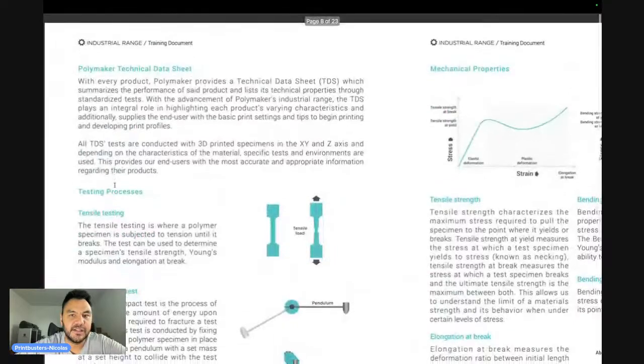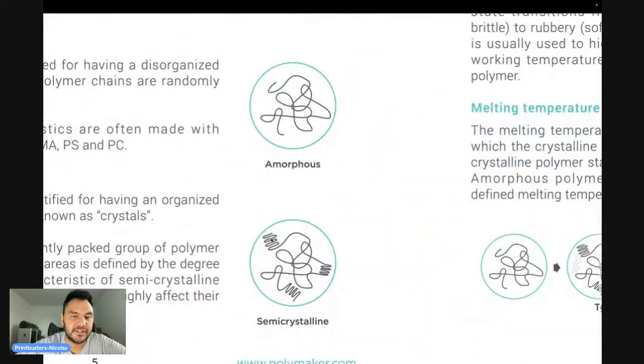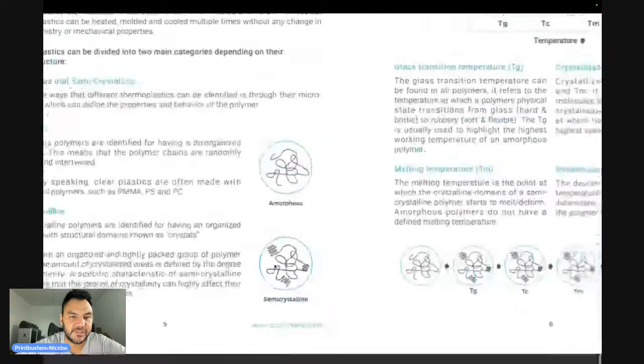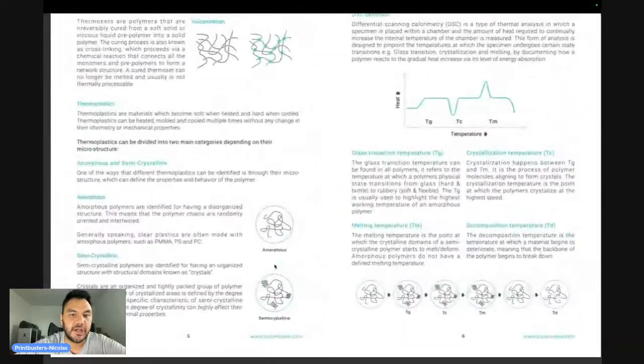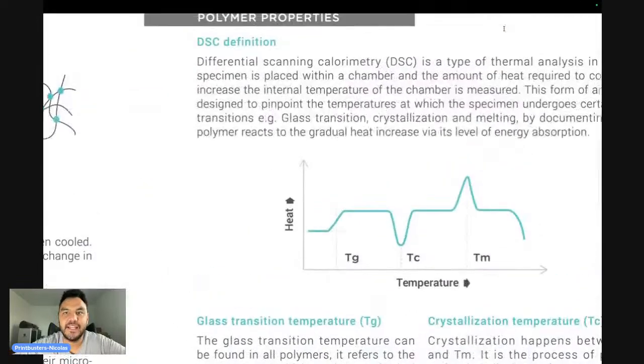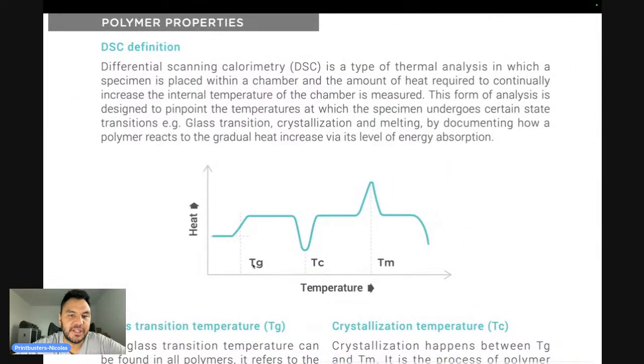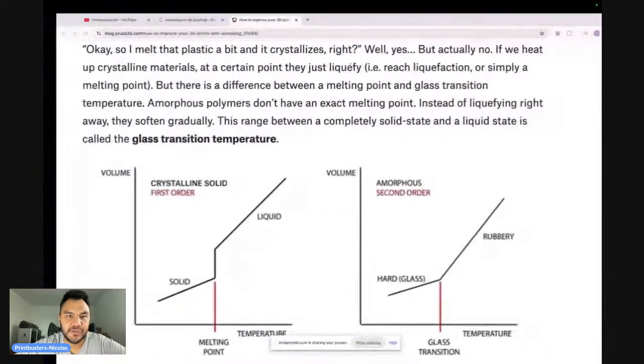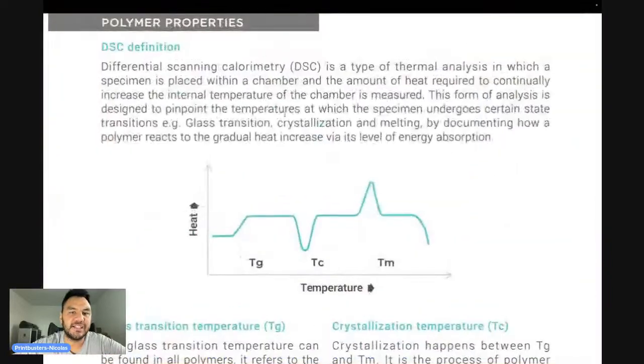And then the semi-crystalline is the same as amorphous, but there are some areas that have a crystalline structure, okay. Sometimes you can have a semi-crystalline that is completely amorphous, and you have to crystallize it. Okay, you have to, for example, anneal it, so it starts creating the crystals. But an amorphous material, even if you anneal it, will stay amorphous, right? It's not going to create the crystals. Okay, and then how do I explain glass transition temperature, crystallization temperature, and melting temperature, right? I know here they explain it in a certain way, but for me, I explain it in this way.